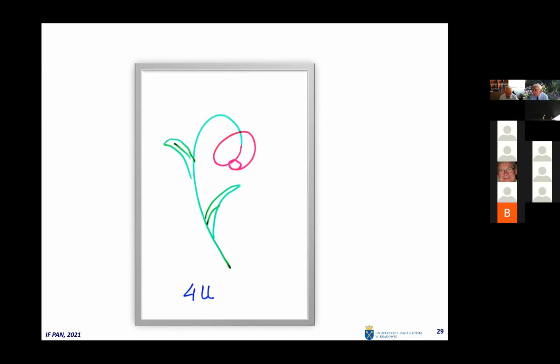Now about Scalapino's 4 electron volts. The problem is that if you have a single band model, then the principal problem, which is why we also did the three band model, is this: when you want a t-J-like antiferromagnetic interaction and get 0.1, 0.12 electron volts, you must assume that U is extremely small. This comes from the mapping from three band model into single band model. Whereas in the three band model, you have realistic U, 8, 10 as the experimentalists observe, and still get similar results as in the single band model, but in the single band model you have to change U in order to get the same value of exchange constant. The qualitative results, angular dependencies, and so on, are the same. So there is a principal difference with the value of U.